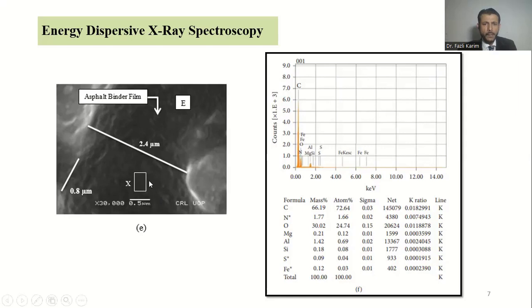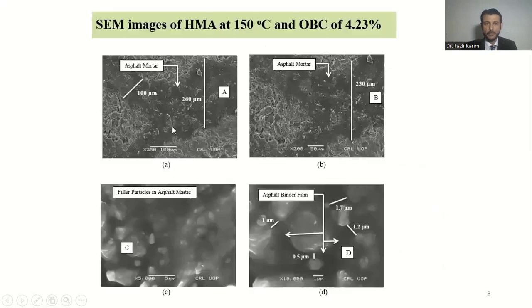Now, in order to verify the existence of pure asphalt binder film, a point X was marked and the elemental composition of the asphalt binder film was determined. And we found in this configuration only the elements of bitumen, which guaranteed that the existing cover is really that of bitumen.